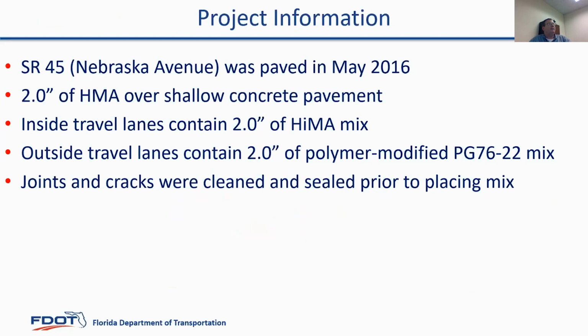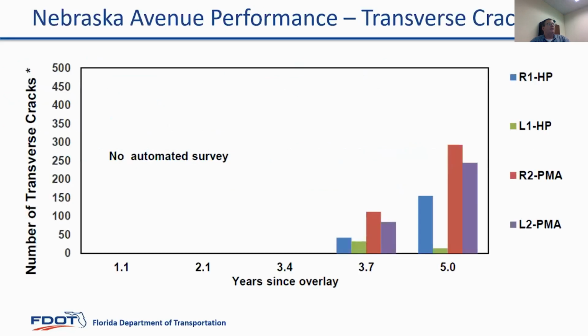So the plan was to do high polymer binder or HiMA binder in all 4 travel lanes. But unfortunately, since this was kind of in the early stages, we didn't have enough HiMA binders. So only the 2 inside travel lanes were paved with the high polymer binder. And then the outside 2 travel lanes were paved with our conventional mix at the time, which is a polymer modified PG76-22 mix. So again, you had polymer in every lane, but the inside 2 lanes had the high polymer, the outside 2 lanes had the conventional mix. They did clean and seal the joints and cracks prior to overlaying it, so we did get a little bit of help there. But I want to show you the performance difference.